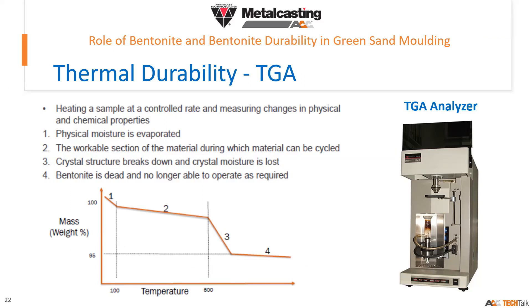If you are able to get a longer temperature range, the material will be able to recover and recycle in more quantity in subsequent cycles. The third portion is where the crystal structure breaks down and crystal moisture is lost. The fourth section is where bentonite degrades and is no longer able to operate as required.